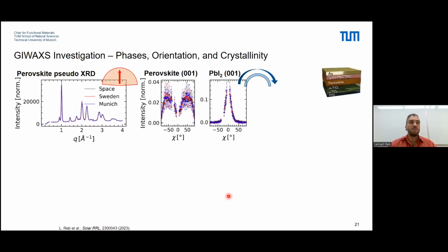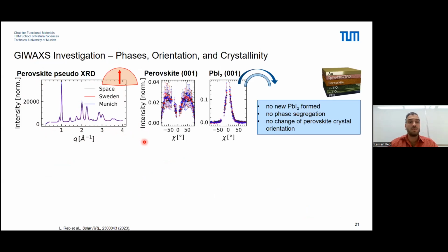Let's go to phases, orientation, crystallinity measured with GIWAXS. So here I'm showing you the pseudo XRD, this radial integration that you have seen before. And what we can see from this one here is that no new lead iodide occurs. We have no phase segregation. So this is all stable. And also the orientation of the reflexes, by doing an azimuthal integration, seems to be totally stable. So the perovskites, in terms of crystallinity, they are stable.